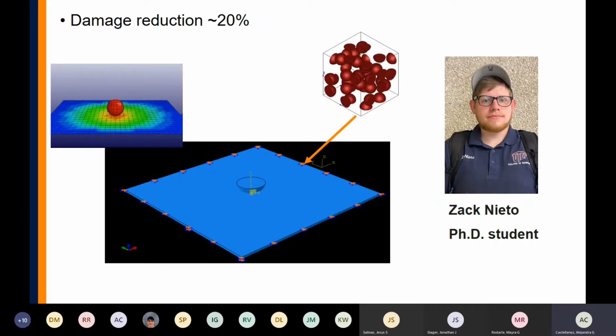So again, all of this, we have found out that there's a reduction of around 20% in the damage by adding this new interlaminar reinforcement. So we're currently in the process of developing an impact model because, as I mentioned before, my research group not only focuses on manufacturing laminates and seeing how the materials fail and why they are failing, but also we look at how we can create computational tools that can predict that damage, that can tell you, okay, if you impact it with a certain mass or with a certain velocity or with a certain impact energy, what will happen?